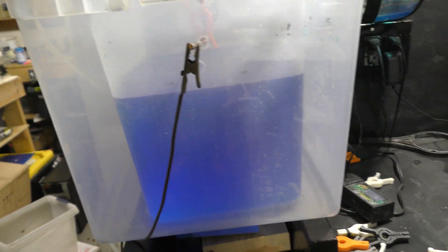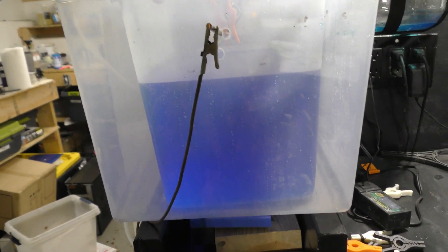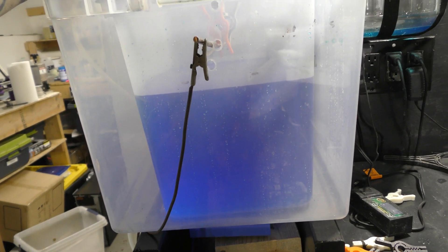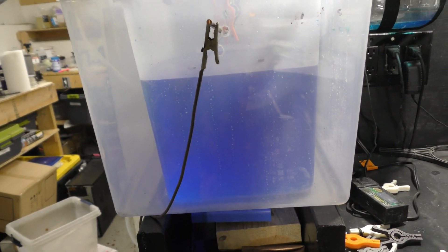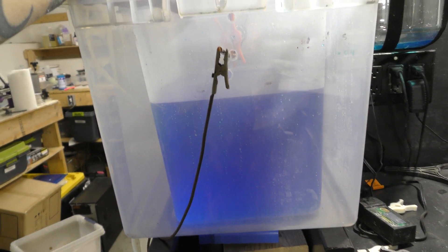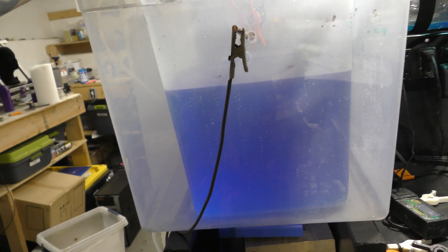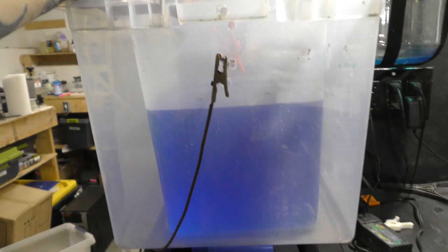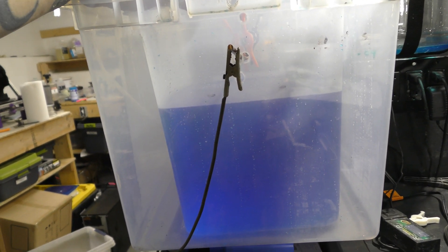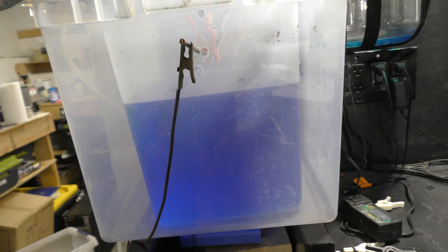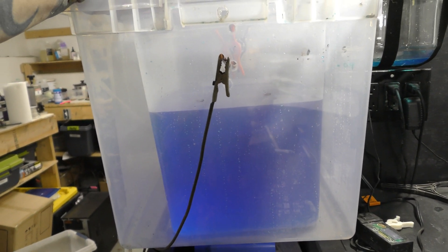This is an electroforming tank. What I've learned from my past was never let it dehydrate. The reason is the sulfides build up at the very bottom, the acid loses its acidity, it turns into a powder. When you go to rehydrate your tank you're going to have an awful contamination issue of super sulfides. You're going to want to re-pH level your tank so now you have extra sulfides, and the acid and sulfide balance becomes way too far off. You have to filter that probably four or five times. Done this in the past, never do it again.